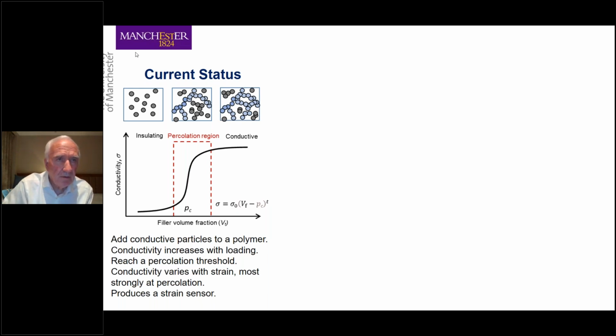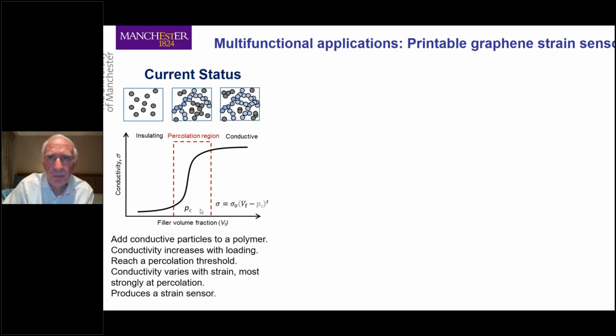Essentially, if you take any conductive filler and add it to a matrix, a particular polymer matrix, usually the polymer, of course, is insulating, so has a low conductivity. But as you increase the volume fraction of conductive filler, the conductivity shoots up through this percolation region, and then the material becomes conductive. So we get to something known as a percolation threshold. And this is where we can produce strain sensors with particularly high levels of sensitivity. So I want to show you about printable graphene sensors for strain measurements.